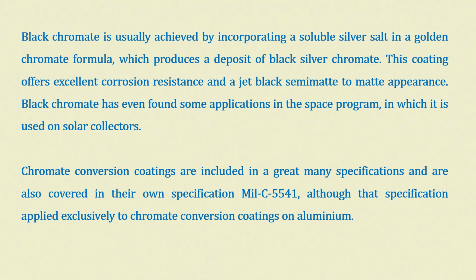So, the black silver coating is produced from a golden coating formula by introducing a little bit of silver. This type of coating offers excellent corrosion resistance and a jet black semi matte to matte finish. Black chrome has even found some applications in space programs, used on solar collectors, very important now, because in stellar space the only source of energy would be sunlight. Chromate conversion coatings are included in a great many specifications and also covered in their own specification of MIL C 5541, although that specification applies exclusively to chromate conversion coatings on aluminum.